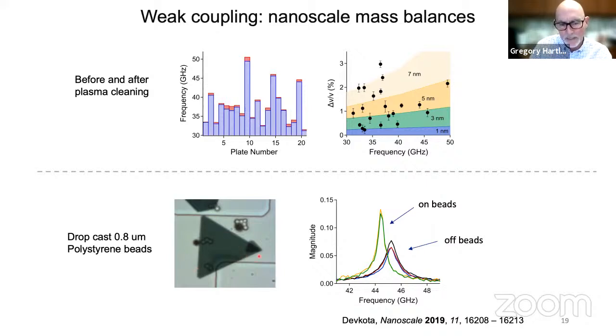This is a nanoplate where we have tried to coat with some polystyrene beads. So you can see the plate here, and these little circles here are the polystyrene beads. So what we did in this experiment is we did measurements where, or rather Tufan did measurements where, he focused the laser in the region of the plate where there are no beads. And then he did an experiment where he focused the laser on a region of the plate where there are beads. Right, so no matter where you go in the plate, if there are no beads, you always measure the same frequency. These materials are very, very uniform. When you go onto the beads, you measure a different frequency and it is shifted to a lower frequency. So there's, again, a mass loading effect that comes about from adding the beads to the plates.